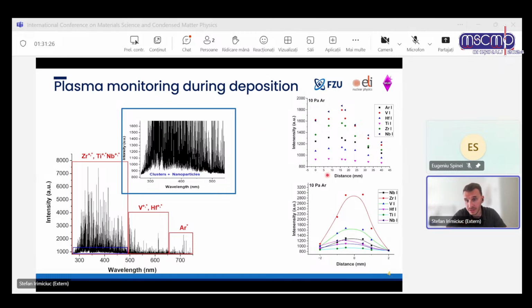So we saw here that with the distance, the plasma has mostly a cosine to the power n distribution, which is expected. The intensity varies with the distance, you see some variation here, but the ratio between elements is the same in every place of the plasma, which means even though it's a non-equilibrium system, the particles travel consistently, and they don't arrive sequentially at the substrate.